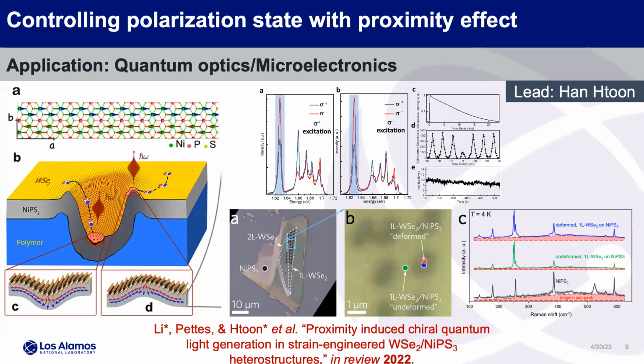These measurements took a long time, so that's why I don't have a map, because you're drifting and stuff. You're trying to optimize how you're collecting the signal versus how much the sample is drifting versus keeping everything at 4 Kelvin. There's a map, but it doesn't look great, so I didn't show it. But the magnon is very, very clear that it's much higher.